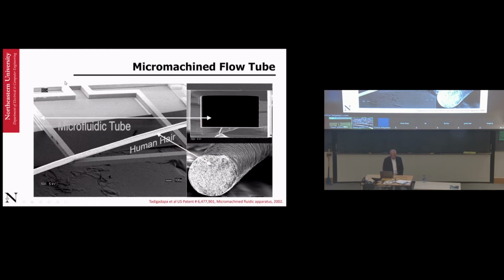You can see here our shape of the U-tube, the first version at that time, with sharp corners. We did silicon to silicon bonding and made this little hole in the middle. This thing is the size of a human hair with a hole through it. It is sitting on a glass substrate, with anodic bonding even then, and a gap of only a couple of microns. Then you have to evacuate it, otherwise the air between the freestanding structure and the glass substrate will squeeze and damp the system, and you will not get a good Q out of it. To get a good Q, you have to do this in vacuum.